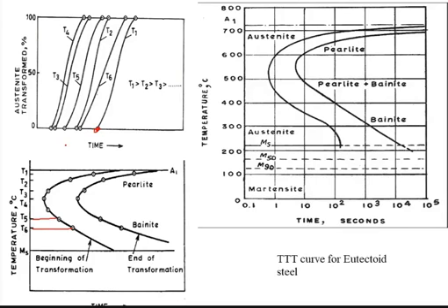As far as our iron carbon diagram is concerned, 0 time is required for pearlite to austenite transformation for eutectoid steel. But practically, we require some time for pearlite to austenite transformation, and this time is the incubation period.